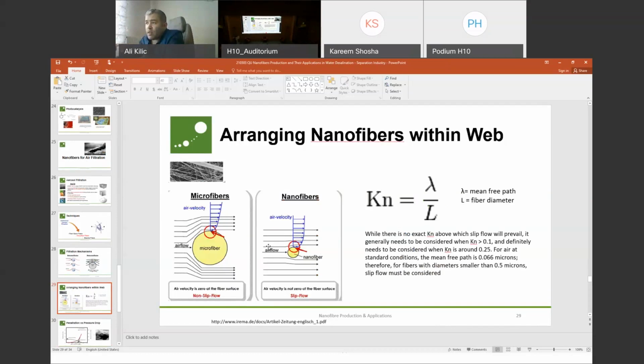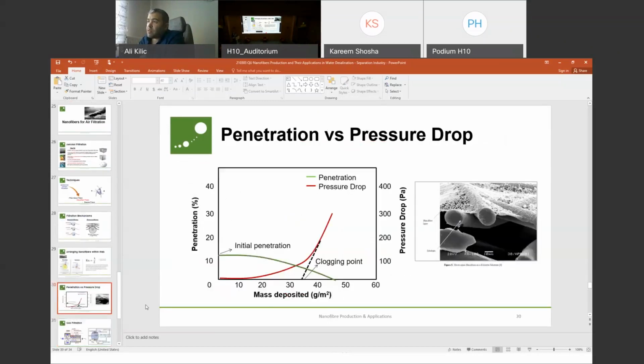If we reduce the nanofiber diameter below 100 nanometers, when the air hits it, it makes a motion which is called slip flow, meaning that the velocity of air does not drop to zero as it does for microfibers. So when we use nanofibers, the air just slips over the nanofibers, and for that reason we are going to be at lower pressure. So a lower pressure drop is again provided by the nanofibers, and this is a graph for penetration and clogging. This is for air filtration.